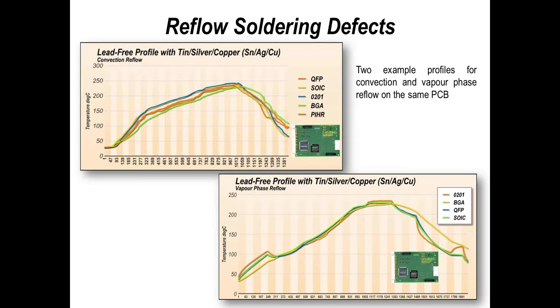There are advantages with going to nitrogen, but again, a good engineer can select a board finish, a solder paste material, even for ultra fine pitch and high reliability applications, and run in an air environment. Doesn't have to use nitrogen. The benefits of vapor phase have been seen because of the movement to lead-free technology and also to do with the advantage of getting good reflow with a low residue paste, perhaps a very small particle paste, without the need of nitrogen in the convection process.